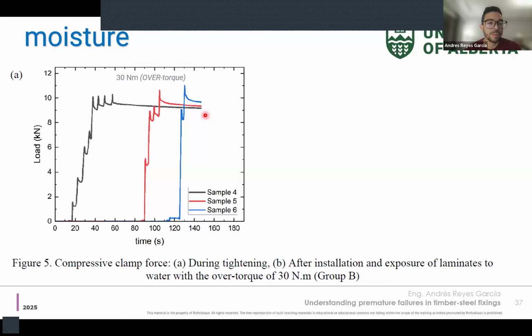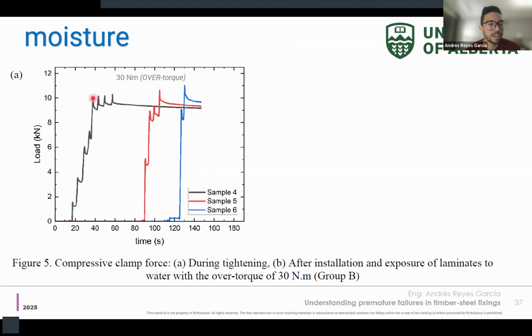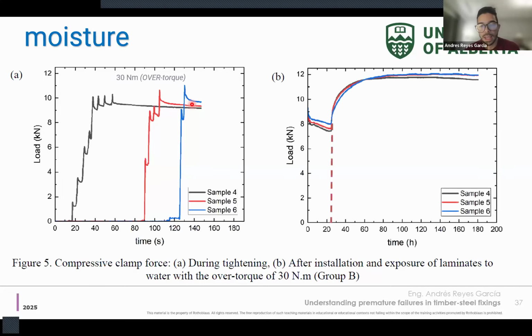When we then put an overtorqued sample of 30 Newton meters, then instead of the initial 6 we had, we are at 10 kilonewtons. And we hit a plateau more or less at 10.9. So we start with a lot more pre-stress. And we have a bigger initial reduction, but then a smaller plateau. And we hit 12. So that means that the higher the over torque, the less is the swelling effect.